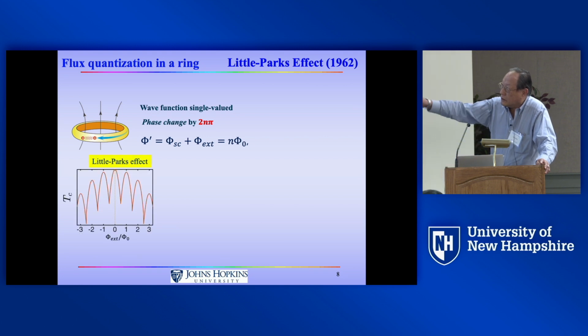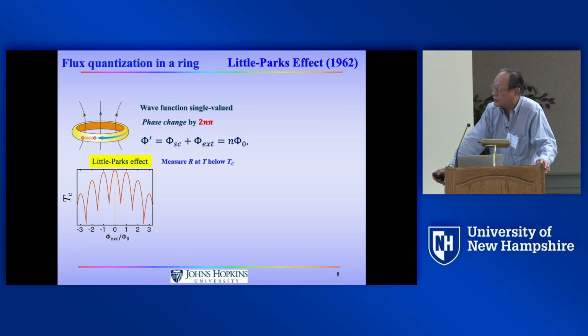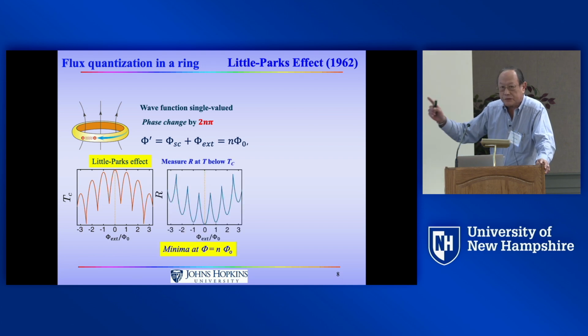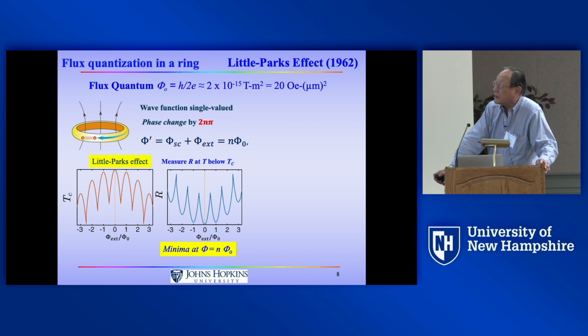Okay, so if you measure the resistance of a superconductor ring at a temperature just below Tc, you will see resistance minima. The minima occur at integer times phi naught. What is phi naught? Phi naught is the flux quantum. If you had to make it from fundamental constants, h over e would be sufficient, but it has to be h over 2e, because nature is telling us Cooper pairs have charge 2e.